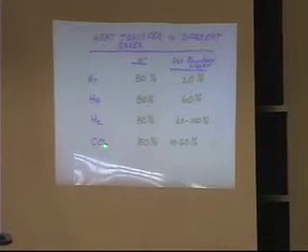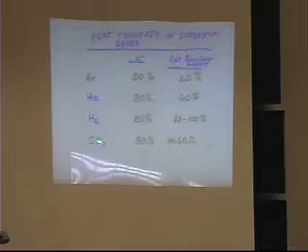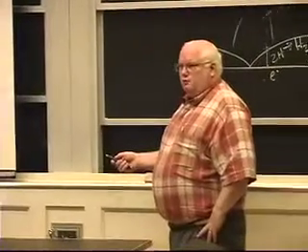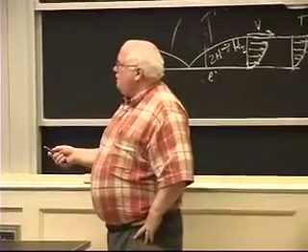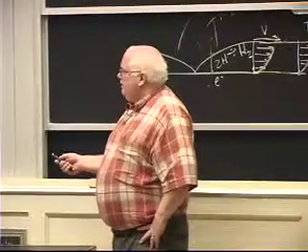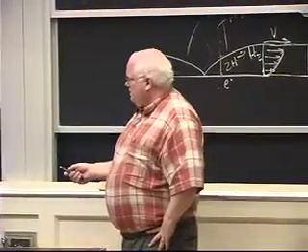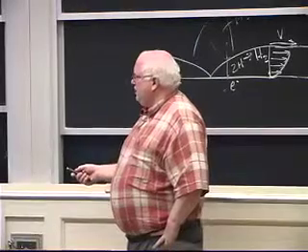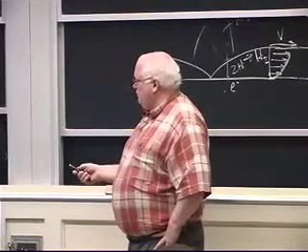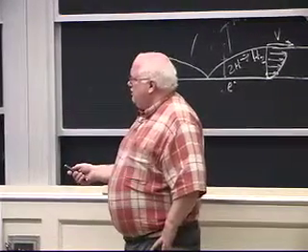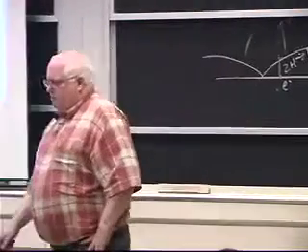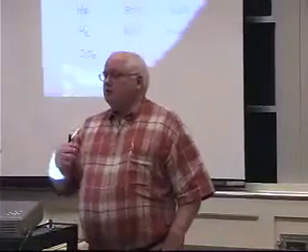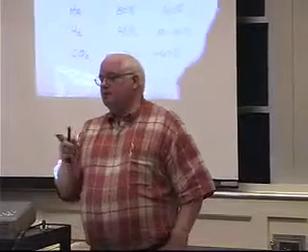So CO2 welding, which we tend not to use for high-strength steels because it tends to oxidize some of the alloying elements of the weld metal. We tend to use argon with 2% oxygen as a shielding gas, or argon helium mixtures, sometimes with a little bit of CO2, like 2%. Anyway, there is an improvement with CO2 depending on how much CO2 you have. Okay, so heat transfer in gases changes on these principles.